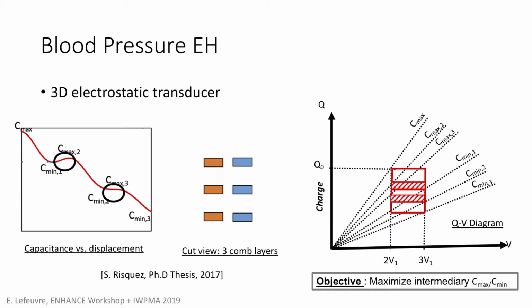Then we start the second loop. So this is the second loop. And then finally, we totally close the loop here. And the harvested energy is actually the total loop plus the small loops inside. So if we design the system well, we can have a larger Cmax and a smaller Cmin here, larger here, smaller here, and larger intermediate energy conversion cycles. So this way we can have a very, very strongly coupled system with reasonable voltage. That's the idea, to increase the energy for a voltage as low as possible.